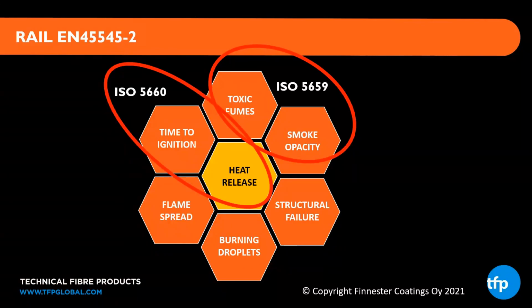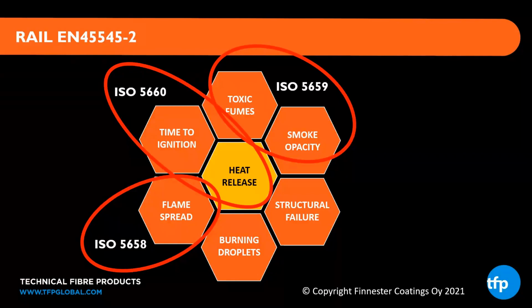ISO 5660, which is the cone calorimeter, is used to assess the heat release. How much energy does the part release when it burns? And ISO 5658 is used to assess the flame spread, the surface flammability. How quickly will a part burn in a fire event? So you can see this is a really all-encompassing standard that covers all areas of FST. The F, the fire, is covered with the flame spread and the heat release, and then the S and the T, the smoke and the toxicity, is covered by the 5659.